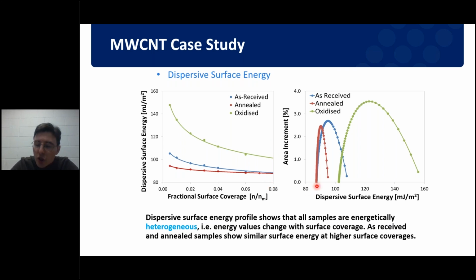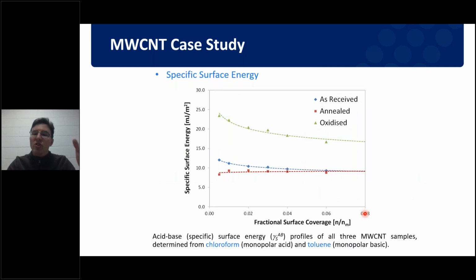So this distribution overall has drifted to the right, and the highest energy sites have a greater disparity from our other carbon nanotubes. Now here we were specifically looking at dispersive surface energy. So just the energy that was calculated using my non-polar probes, using hexane, using decane. Now on this next graph, we are looking at the specific surface energy. So how polar is my surface? And we can see a similar trend being observed.